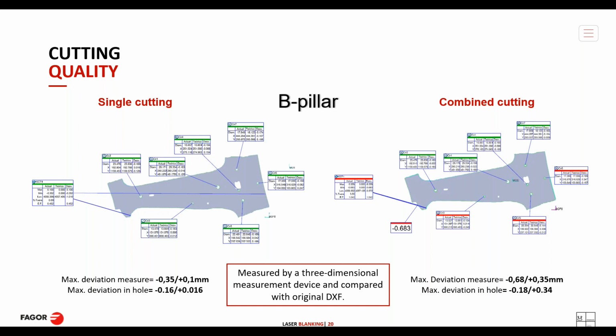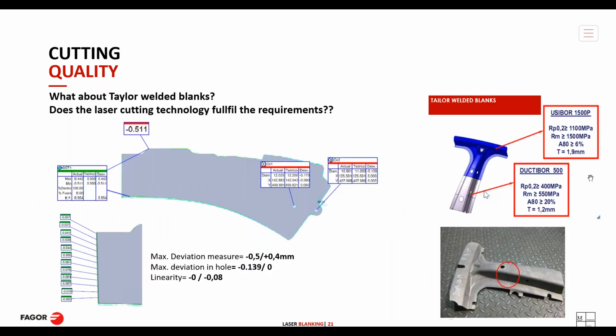On the other hand, if combined cutting would be executed for the same geometry, we can see that the deviation, the tolerance is slightly worse. From minus 0.68 to plus 0.35. And as well, the deviation between holes, the tolerance is slightly bigger as well.